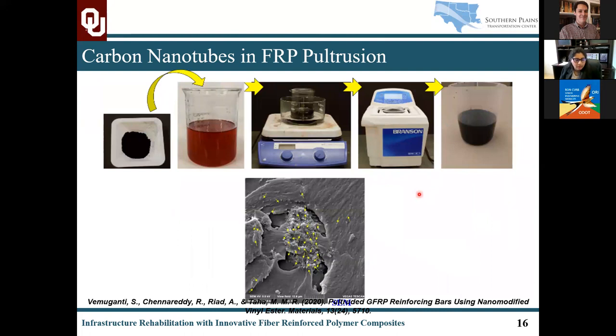The resin modification process resulting in these improvements is fairly simple, with carbon nanotubes measured at about 0.5 to 1.5% or 2% of the weight of the resin. Very small quantities of these carbon nanotubes have shown huge improvements in shear strength. The modification process involves mechanical stirring and an ultrasonication bath in order to break the van der Waals forces between the carbon nanotubes. These nanomodified resins can be analyzed for how effective the dispersion process is using scanning electron microscopy. In this particular fracture surface, we see a lot of good dispersion of carbon nanotubes in the resin.